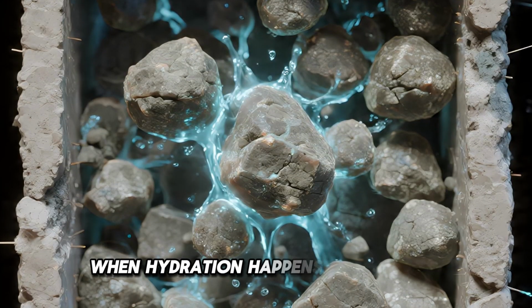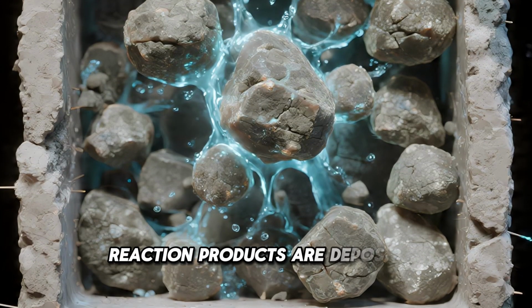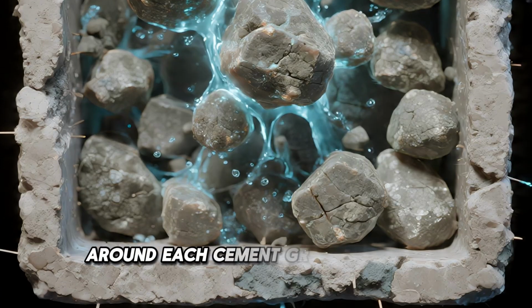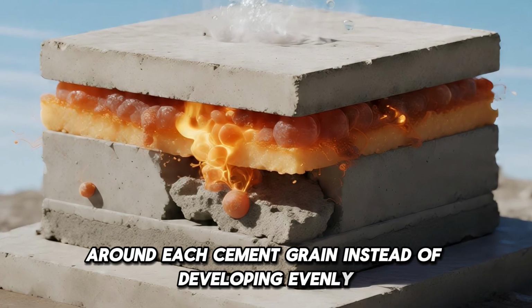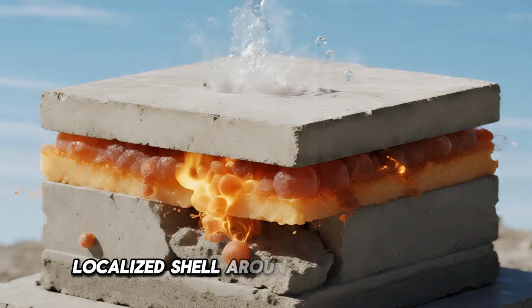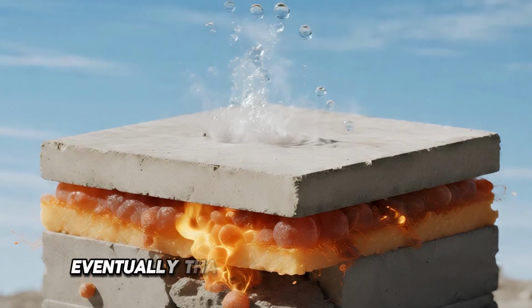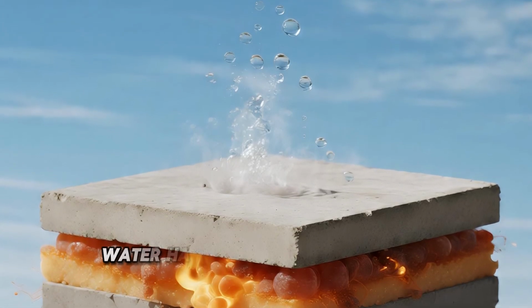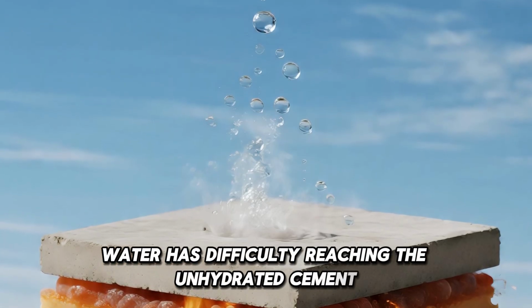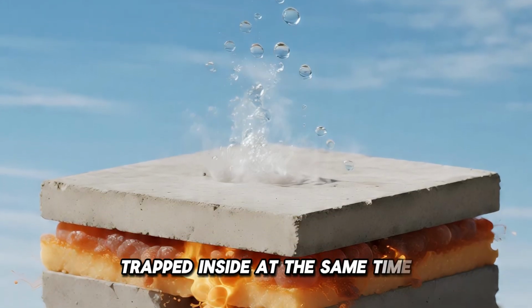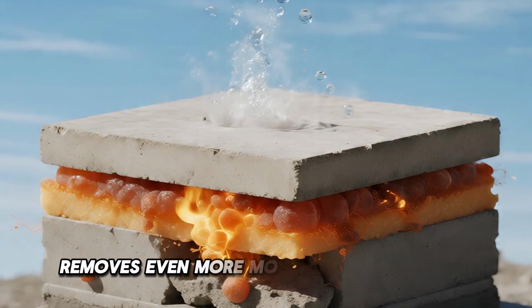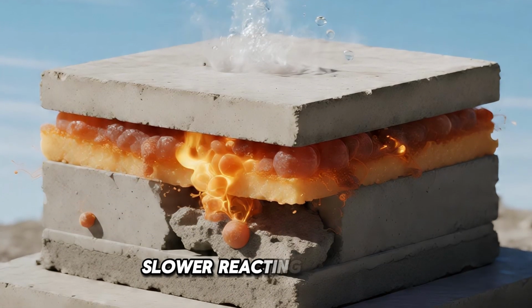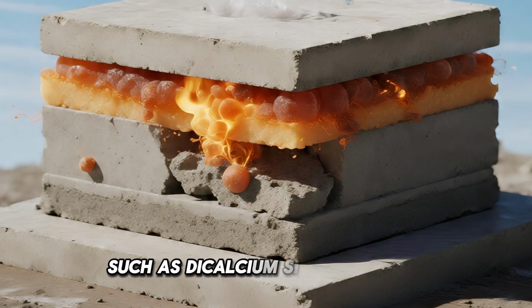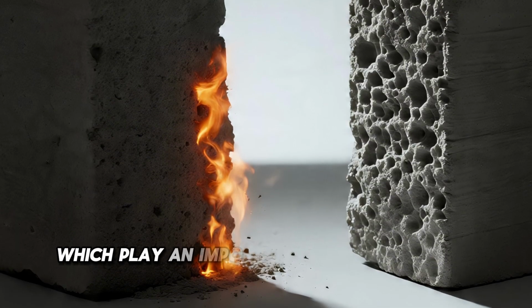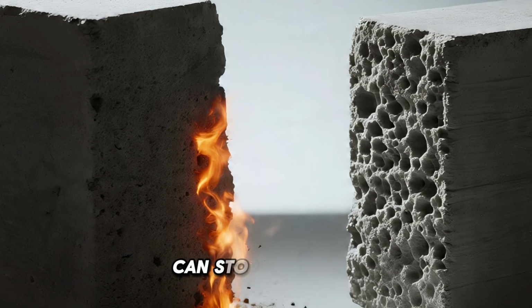When hydration happens too rapidly, reaction products are deposited chaotically around each cement grain. Instead of developing evenly, they form a dense, localized shell around the grain's core. Eventually, that shell becomes a barrier. Water has difficulty reaching the unhydrated cement trapped inside. At the same time, rapid evaporation removes even more moisture from the slab. Slower reacting minerals, such as dicalcium silicate or C2S, which play an important role in long-term strength, can stop hydrating because they are starved of the water they need.